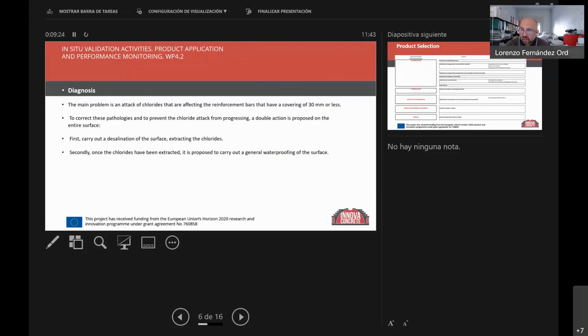And to prevent this, we established a double action, which was first to desalinate, to take all the chlorides from the sculpture. This is something that can be done with some pads, and is done well. It has to be done by hand, but it can be done as a normal practice in restoration. And after that, it is proposed to do a general waterproofing of the surface.